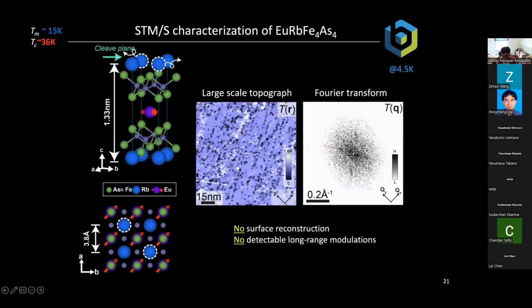One of the things I want to impress on you, because I'm going to show you some data later about the superconductivity: if I just go with my STM and probe around on the surface and ask what the structure of this material is, you will see many defects, and that's because any material in the world has defects in it. But these defects are not ordered, so they have no structure in them. If I take the Fourier transform of this real space image, in reciprocal space, you'll see noise, and this noise is just because of the Fourier transform of these random pixels. But there's no surface reconstruction or other sort of orders in these materials, and no detectable long-range modulations in the surface topography of this material.